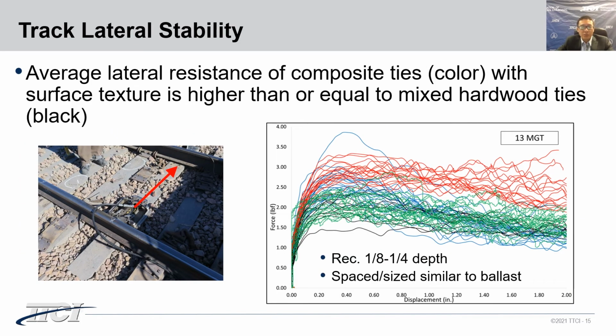The plot on the right shows the force displacement curve from the single tie push test for composite ties and wood ties at 13 MGT. The colored lines are the three composite ties. As we can see, they had similar or higher lateral resistance than the wood ties, which are plotted by black lines. Based on the single tie push test results, we had a couple of recommendations in the AREMA manual. The spacing of the surface pattern is recommended to be similar to the size of a nominal ballast particle, and we also recommended a depth of 1/8 inch to 1/4 inch for the surface texture.